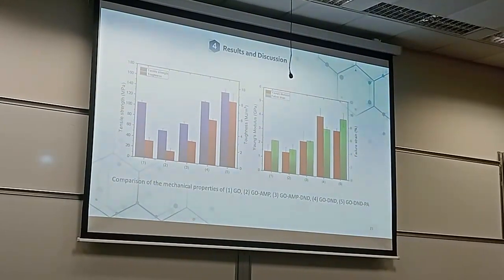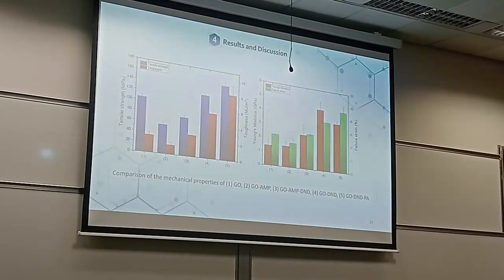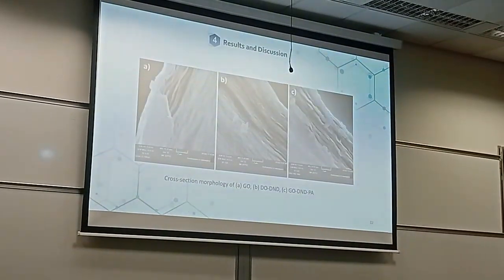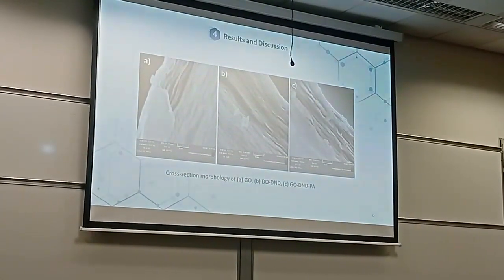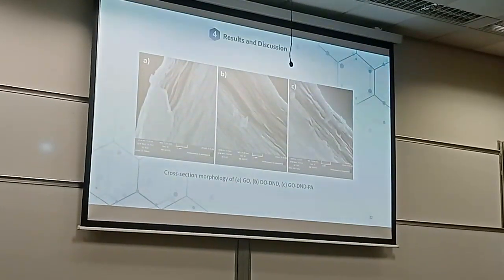is a bit normal because it didn't have the layers to arrange together. Then when introducing the nanoparticles, it increased a bit. But when doing esterification directly, we can see that there was a good increment. And then when introducing the polymer, it got much better, the Nacre-like structure with nanoasperities together. Then we verified by SEM if this ternary system is compact and the thickness decrease.